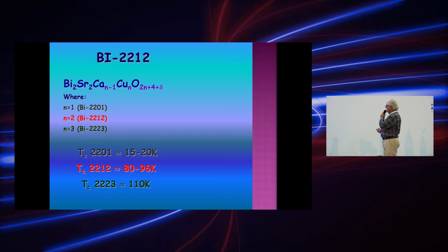Now we know bismuth-based superconductors, given this formula, have three phases. The first one is the bismuth 2201 phase, which has a Tc value of 15 to 20 K. The 2212 phase has a Tc between 80 and 96 Kelvin, and the 2223 phase has 110 K. Because of the stability of the 2212 phase, most people are studying these materials.